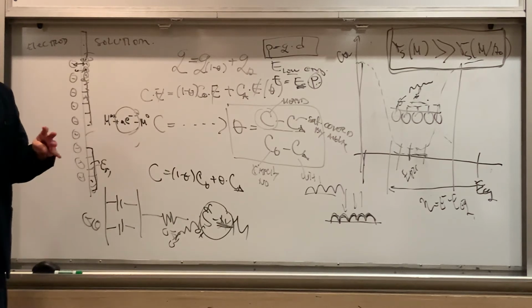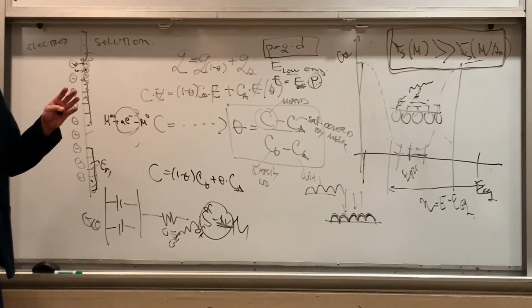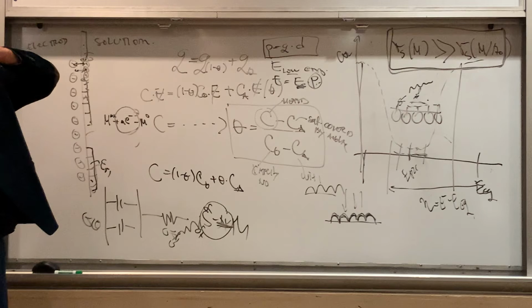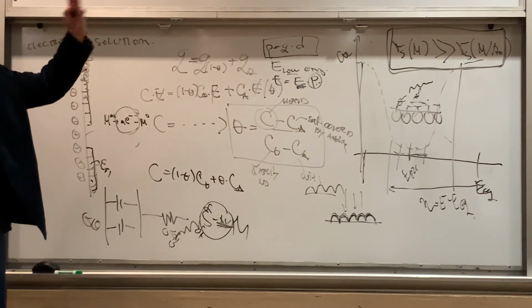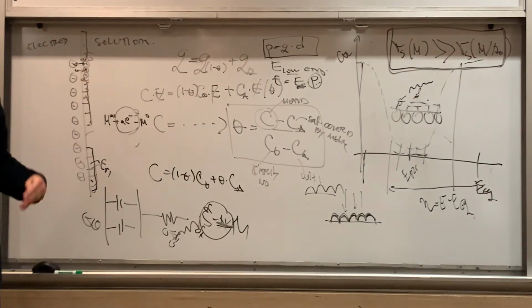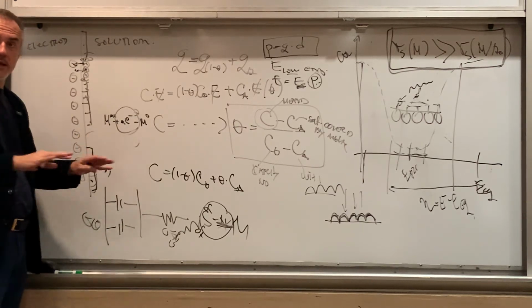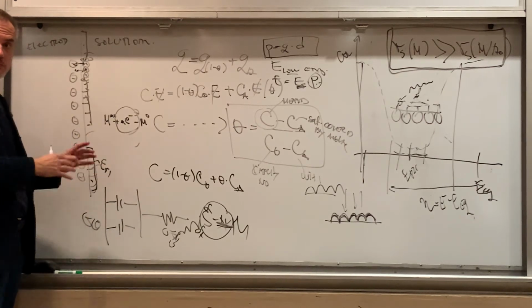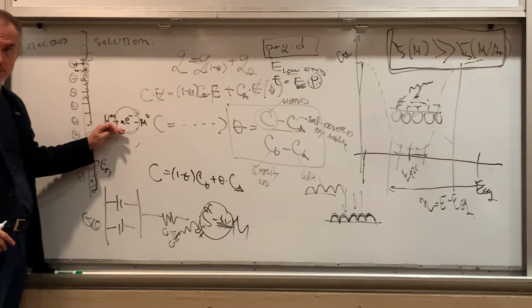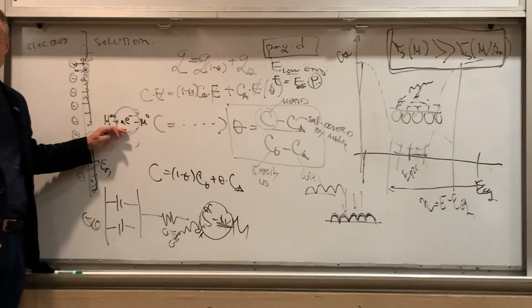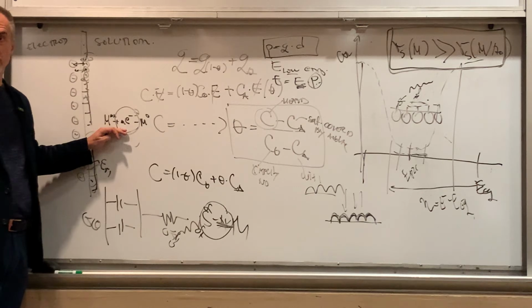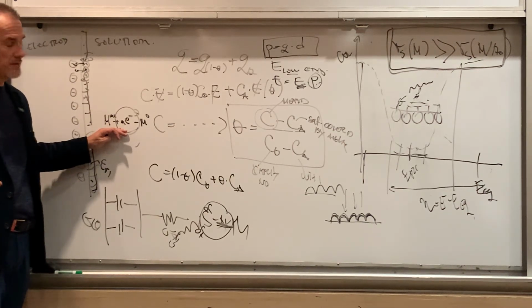And you remember we talked about that, but there is a free energy of activation which is in the kinetics of electrodeposition. We discussed the Butler-Volmer equation and so on. So we are changing the milieu, or energy milieu, by adsorption of additives, so the charge transfer process becomes more difficult, number one. Generally more difficult. Not necessarily always, but generally more difficult.